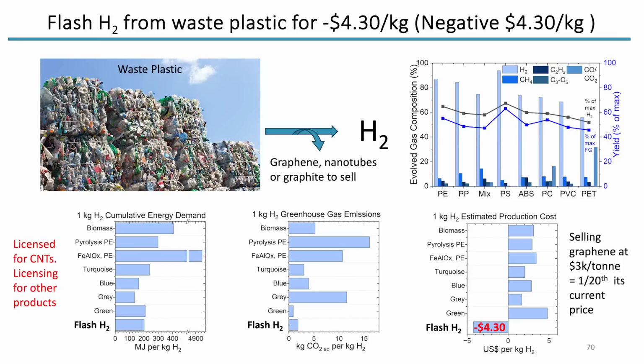So when you look at this, when you flash this waste plastic, here's how hydrogen is normally made. Here's all the different routes. The way it's normally made is this gray route. Gray route is you take methane and you do nickel reforming on it, the steam nickel reforming. You take a nickel catalyst, steam, and methane. You heat that up and you get CO, then CO2, and H2.